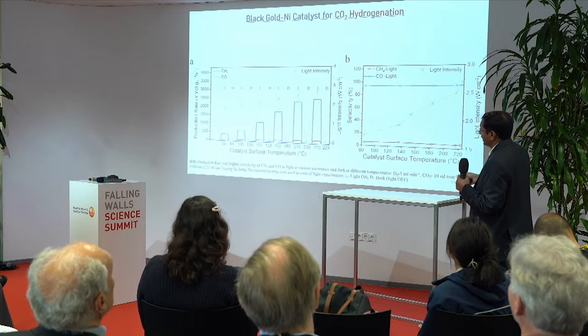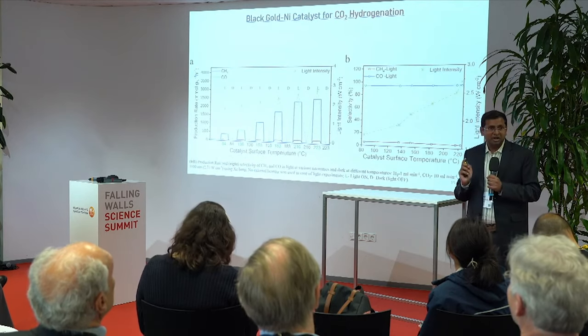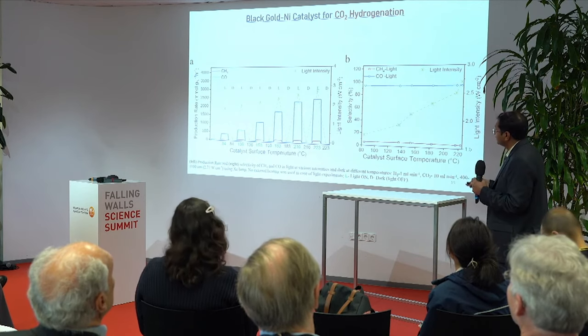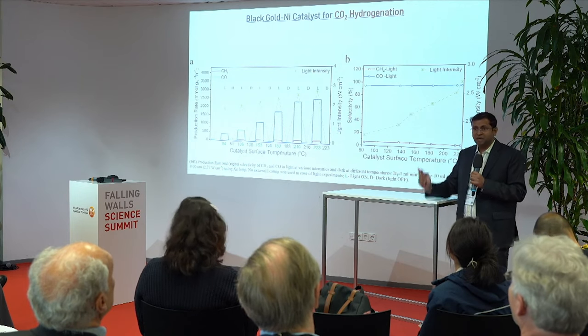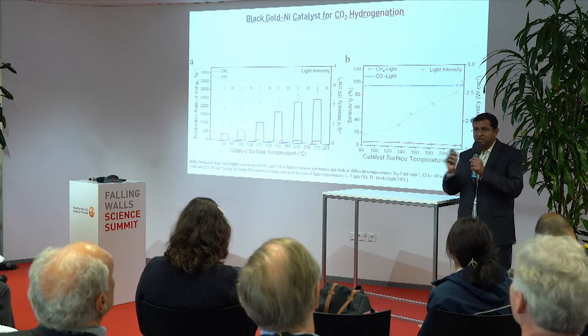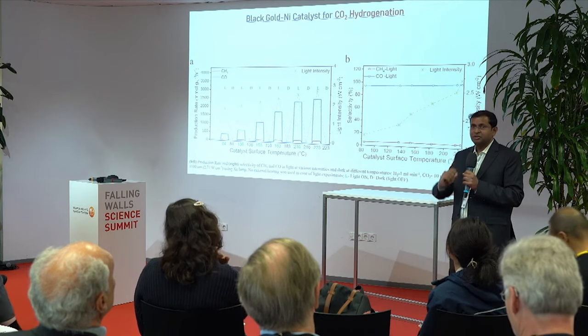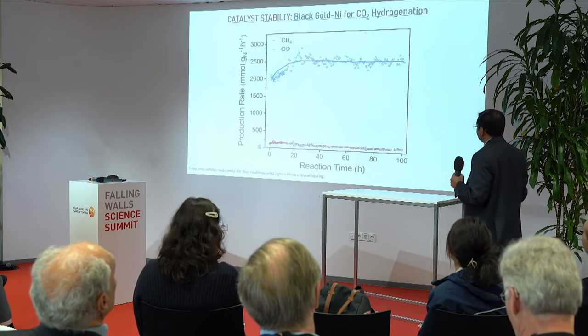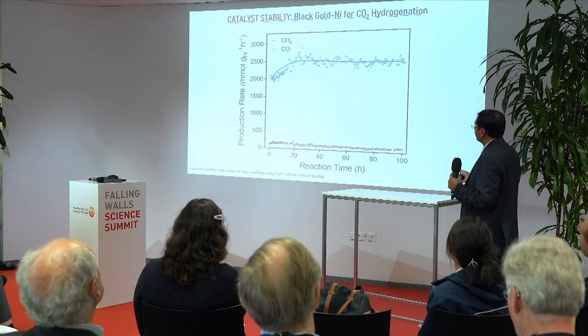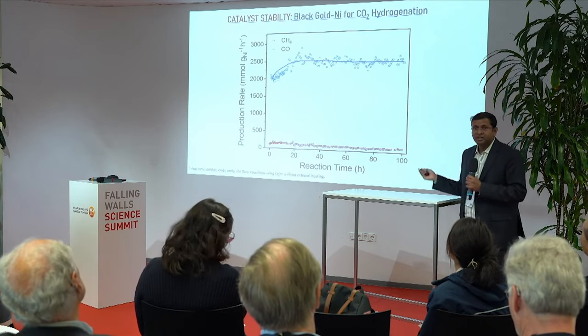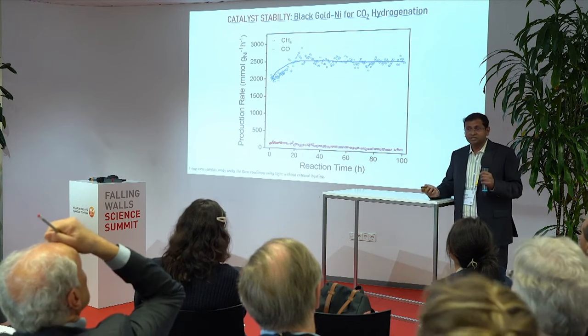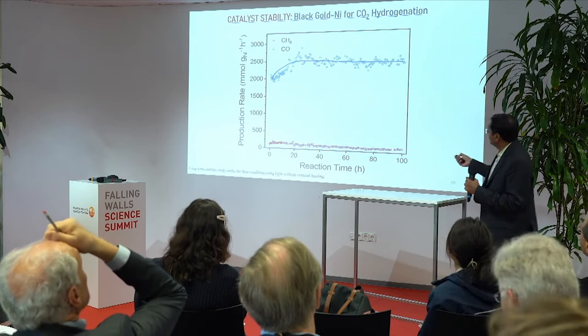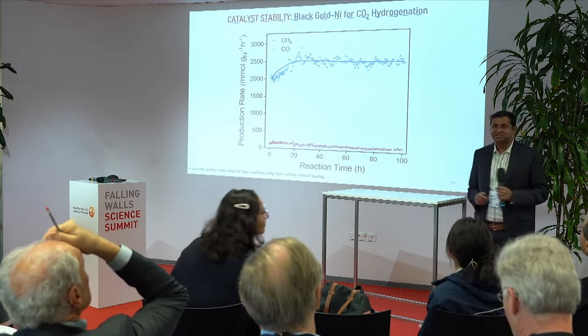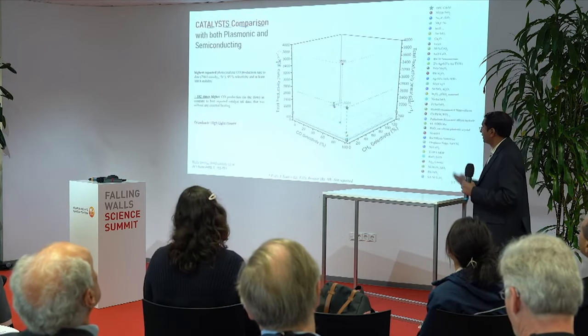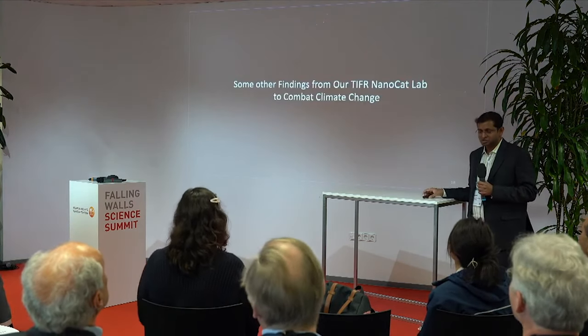Now look at the catalytic activity. It was 1.5 micromole per gram using black gold. As soon as I add nickel, it changed to 2,500 millimole per gram. It's just a huge jump in the activity by simply tuning how the electron behaves when you are creating those hot electrons. Right, so it's a stable material, right? It has a stability up to 100 hours. Ideally, in reality, it should be for years, which you cannot test in the lab, but this spectra shows that it is active for a longer time. Right. With that, I would like to thank you for listening to me.